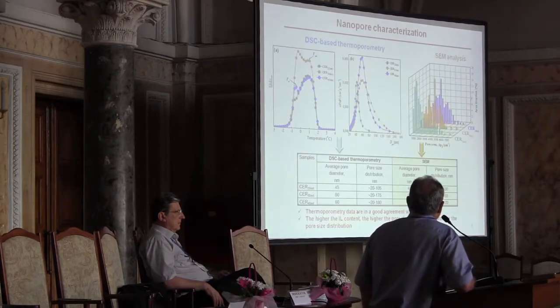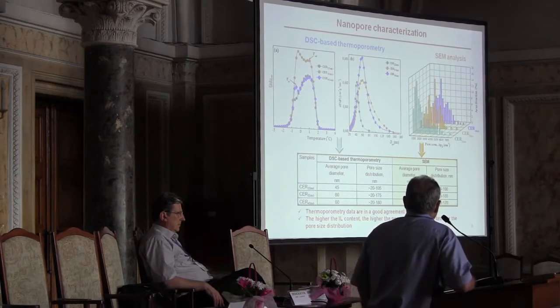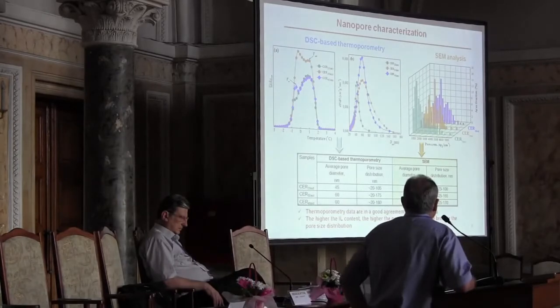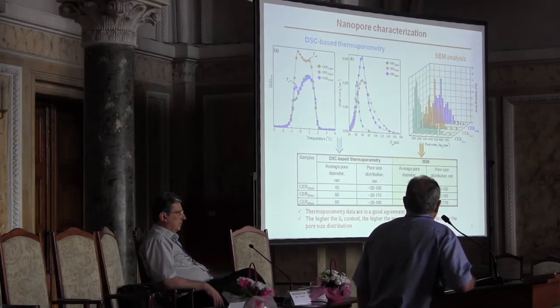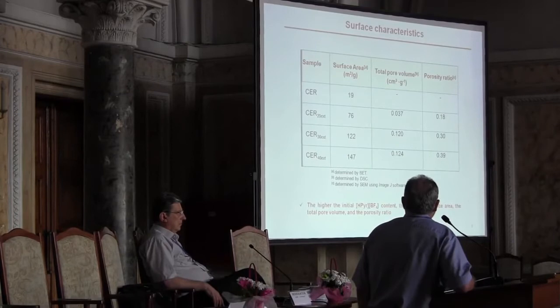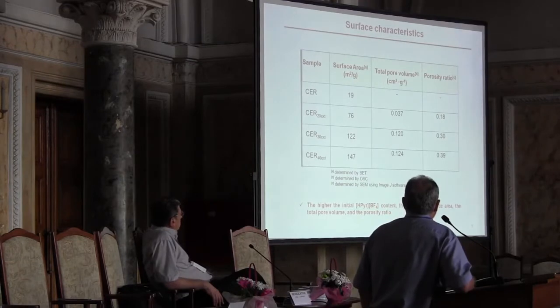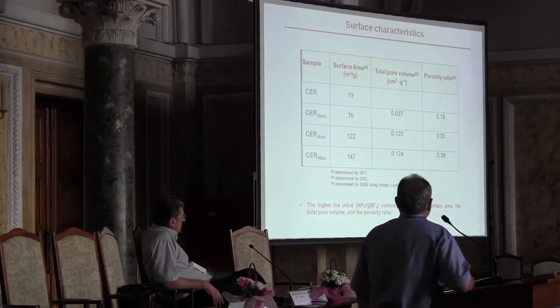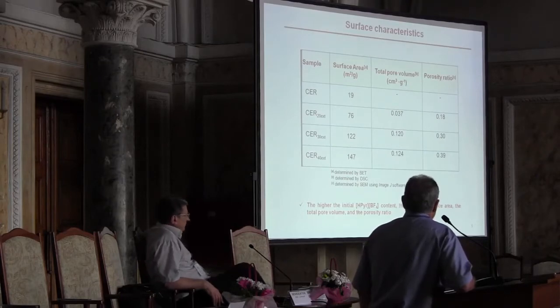Then the nanoporosity was characterized using two methods, DSC-based thermoporometry and SEM analysis, and we found that they are in good agreement, and average pore diameter was between 45 and 60 nanometers, and pore size distribution was between 20 and 180 nanometers. Then surface characteristics: surface area increased, and total pore volume also increased with increasing of ionic liquid content in the initial composition.